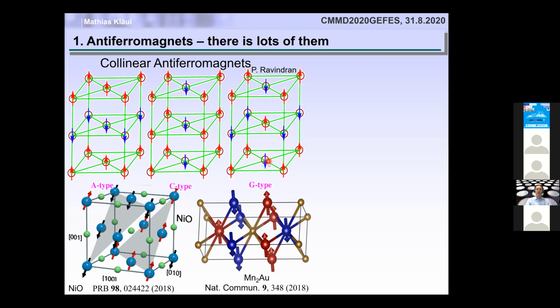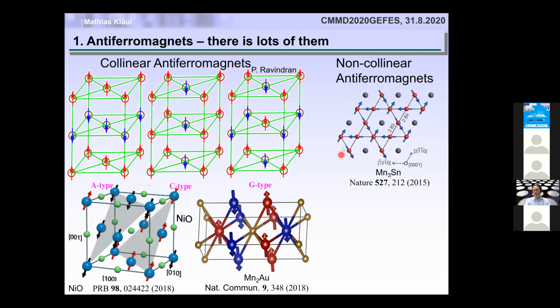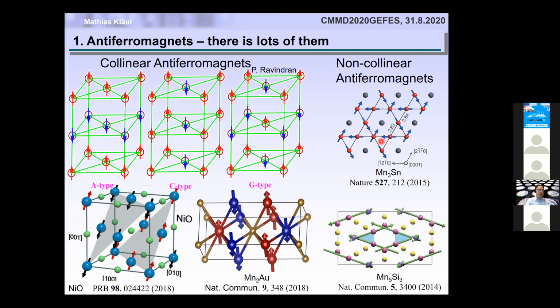And now these are all systems where we actually have so-called collinear antiferromagnets, meaning that all the spins of the two sublattices are pointing either in the parallel or anti-parallel direction, but you can make life even more complex by going to very exciting non-collinear antiferromagnets, as shown here, where you see the spins point in all kinds of directions, but again, within one plaquette, the spins actually cancel out to zero net moment. And then for the ultimate complexity, you can have non-collinear and non-coplanar antiferromagnets, where you see here that there are spins pointing out of the plane towards us or away from us, and that just makes it extremely complex to look at these type of systems.